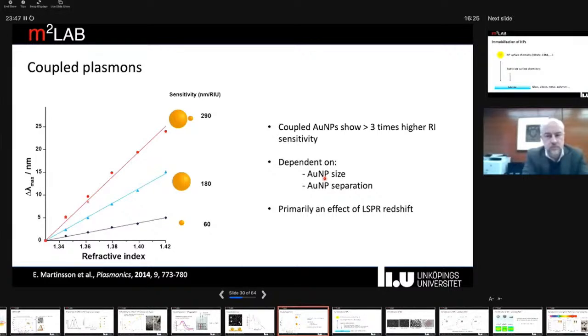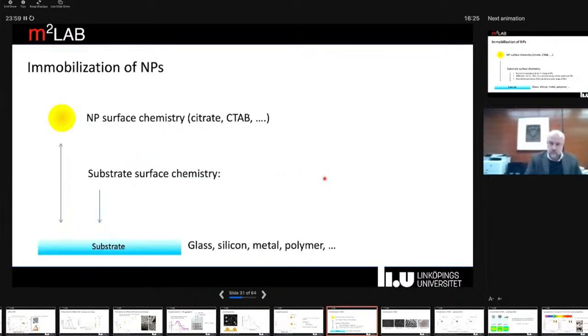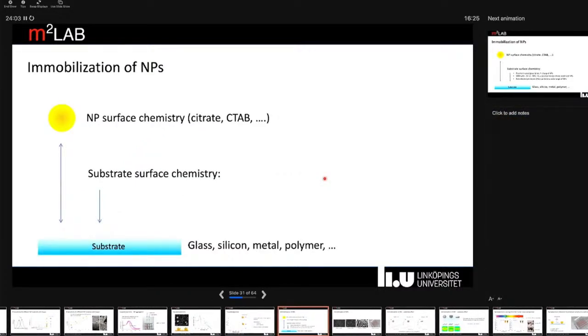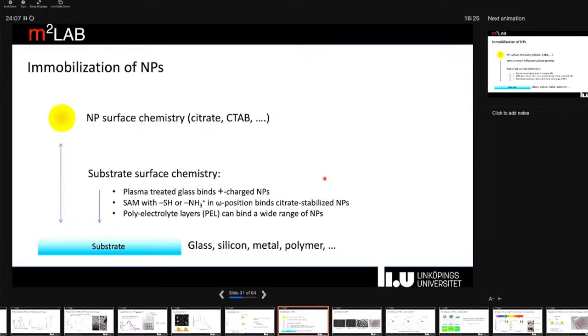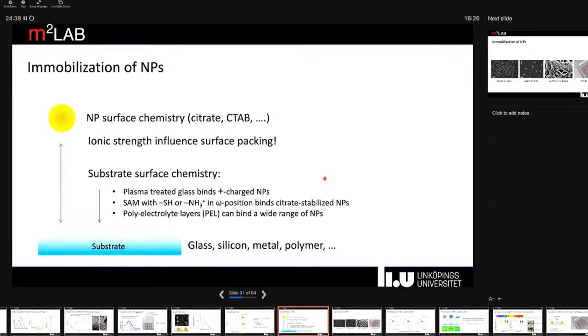And in this case, you probably noticed that we also used immobilized particles, and that's one of the key advantages with a refractive index sensing area, that you don't have to work with particles that are suspended. And there are various ways to immobilize particles, and you can use all sorts of different substrates such as glass, silicon, metal, polymers. And then you can tune the surface chemistry of these substrates, for example, by plasma treatment or by self-assembly of monolayers with different terminal functionalities, or just use polymer adsorption in order to bind nanoparticles to the substrate. And then, of course, you can also adapt your nanoparticle surface chemistry to work well for this purpose, as well as modulate the ionic strength to, for example, increase or decrease packing of particles on the substrate.